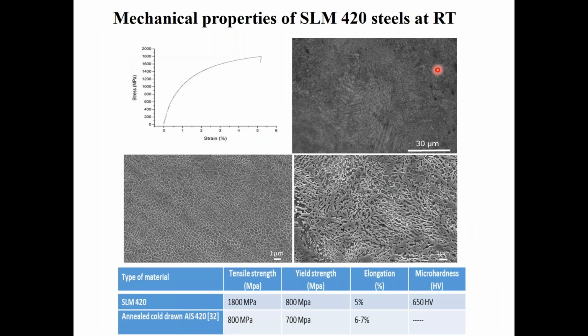So this is the third steel that we built, the mechanical properties of SLM 420, which is a martensitic steel. You can see the SLM structure, that is a hierarchical structure, gives us very promising properties, 1800 megapascal strength. If we compare it with the annealed cold drawn 420, the tensile strength is 800 megapascal. Elongation is slightly low, but it is comparable with the annealed sample.